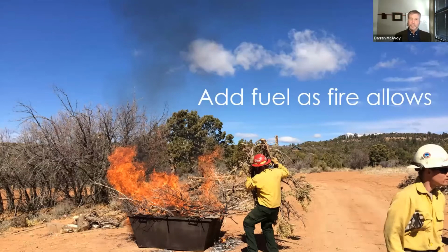We add fuels as the fire allows, just like tending a campfire. If you put on too much on a campfire, it's just going to smother it. If you put on too little, it's going to burn out. So again, a common sense approach. In this example, we're in southern Utah, south of Moab, Blanding, San Juan County, really dry place, really dry fuels. Here we're adding perhaps 6 to 8, maybe even 10 times the volume of the kiln before we stop the process. And I'll show you more about that here in a second.